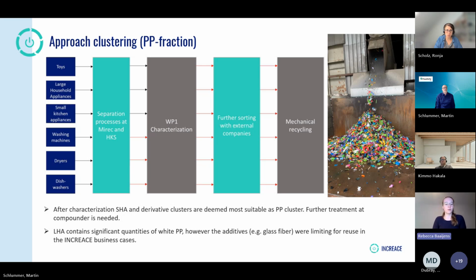And then with the help of KU Leuven, they did the analysis. And then it was found that the small household appliances, but also toys and kitchen appliances have polypropylene fractions that are suitable to further go the mechanical recycling route, so to recompound them and to make new products out. Whereas, for example, with large household appliances, whilst they contain a lot of nice white polypropylene, which would be ideal for further mechanical recycling, they have the problem of glass fiber additives, which does limit its further use due to the additives that are already in there and potential problems with machinery further down the line.